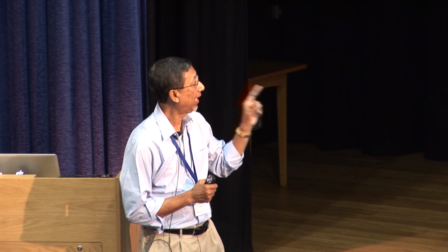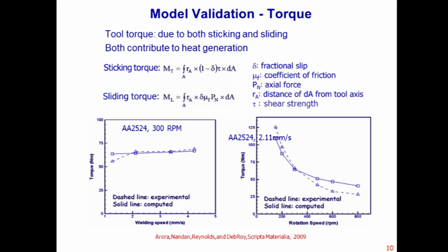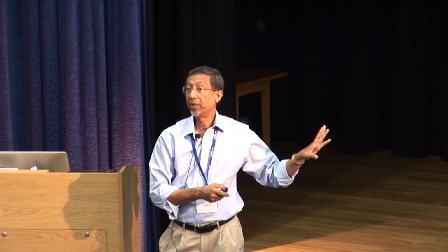So the point is, if we validate the model, then there is a better probability that the thermal cycles we will use for microstructure prediction and for prediction of maps of tool durability are likely to be a little more accurate than if we cannot validate our model. So we have gone as far as we could go with the available results for validating our model, and then we'll be using this. But before I go into the actual field, I want to show you one last graph on how the model results can be useful, because not everything can be measured.